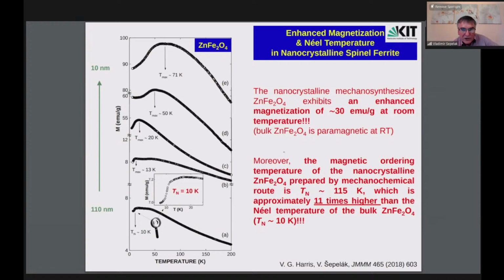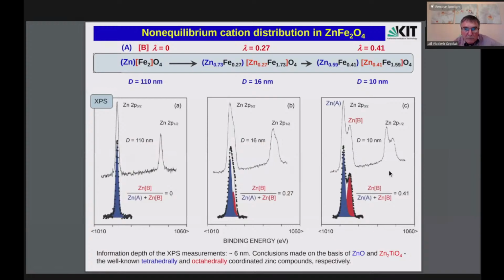To elucidate the origin of such nice properties of this material, we performed surface studies of nanoparticles of zinc ferrite using X-ray photoelectron spectroscopy. You see here the bulk material, with a crystallite size of 110 nanometers. We no longer consider this material nanocrystalline; we say bulk material. And here is a material prepared by mechanosynthesis with a crystallite size of about 10 nanometers. You see the difference. In the bulk case we have only one spectral component, corresponding to zinc in the A tetrahedral sublattice of the material. Iron is sitting on octahedral sites. In the case of nanomaterials prepared by mechanosynthesis, we have two spectral components, which correspond to both zinc on tetra and zinc on octa sites.